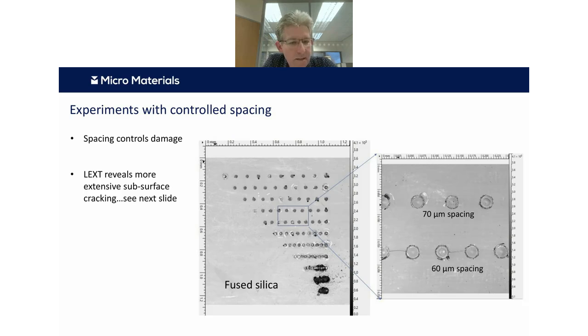So we used laser scanning confocal microscopy to look at this a bit further. One of the things we did then was, instead of using these random impacts, we used controlled arrays. In this case, we've got 10 lines of 10 impacts, and the only thing that's different is the spacing between these impacts. On BK7, under the same set of conditions, there's cracking throughout the entire range. This is for fused silica, and what we can see here is that when the spacing is 70 microns or greater for this set of test conditions, there's no apparent cracking between these adjacent impacts.